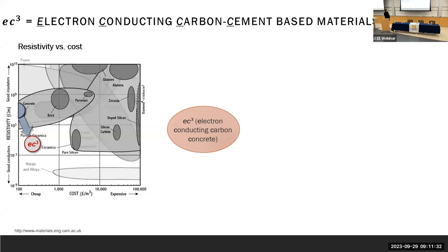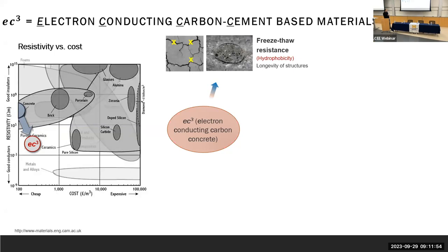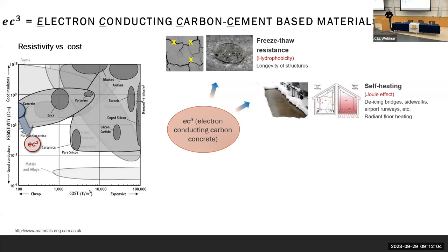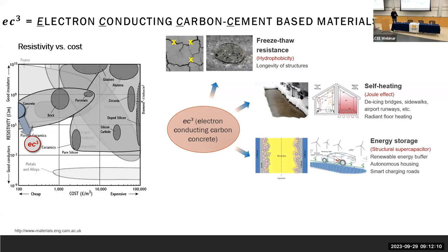And if you now add in this relatively cheap material, carbon black, you increase the cost a little bit, but just marginally, in order to achieve a good conductive behavior in a volumetric sense. And the type of application you can think about is, because of the hydrophobicity, you can get a higher freeze-thaw resistance because of the hydrophobicity of the surface internally and externally. You can use it like a stove plate for Joule effect. You can use it for energy storage, and that's what I'm going to talk about.